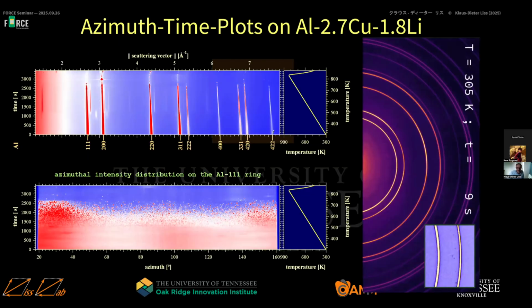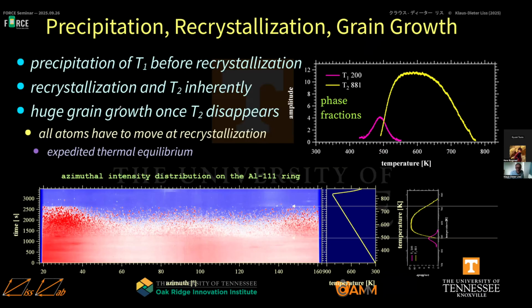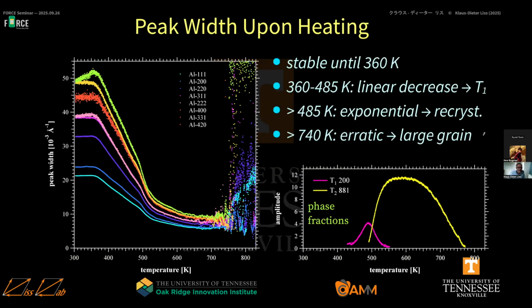So we get this complementary information where we see the microstructure evolution and recrystallization in reciprocal space, so in orientation space, and we see in longitudinal reciprocal space, so normal diffraction, the precipitation of phases, and we can study all that. So we see that here we have one phase coming and going, and the other phase then coming later and going later. So my time is running.